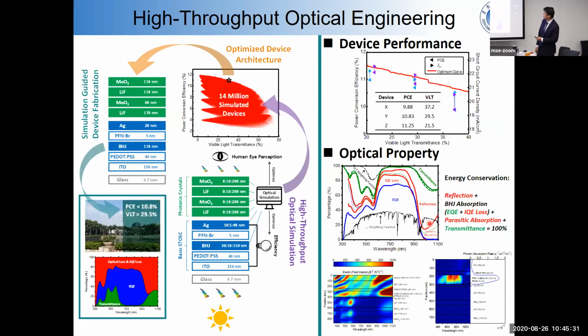And now, when we make the device, it's very close to our simulation result. So now we can easily get a high performance device, but at the same time, we also get a very decent visible transmittance. Here I show you one of the semi-transparent OPV solar cells with 30% transmittance and also over 10% power conversion efficiency. And you can also see this is the transmittance curve. You can see a big peak here corresponding to 550 nanometers, which is our eye sensitivity.